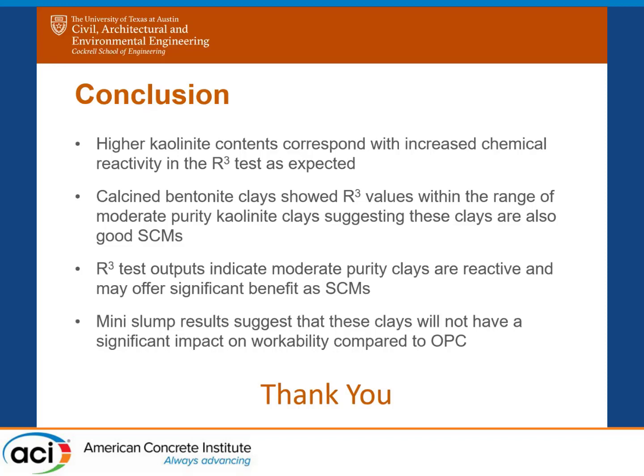The question is from Pranoy Saraneni, University of Miami. He asks, in the R3 test, the heat release or bound water correlates with the kaolinite content. The values for highly reactive metakaolins are around 1,000 joules per gram of SCM. So even a clay with a 30% kaolinite content or low purity is about as reactive as a fly ash, which is about 300 joules per gram of SCM. Would you expect the same durability benefits from such a low purity clay and a class F fly ash, broadly speaking? You didn't really touch on durability in your talk today, so I don't know if you want to extrapolate there, but he's basically asking for impure clays, how does the performance compare to fly ash?